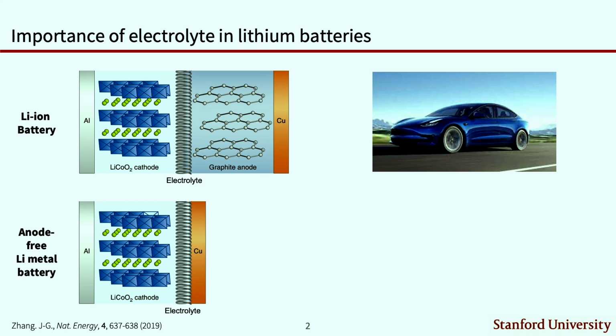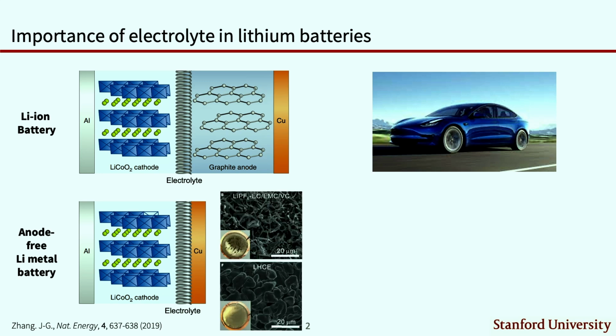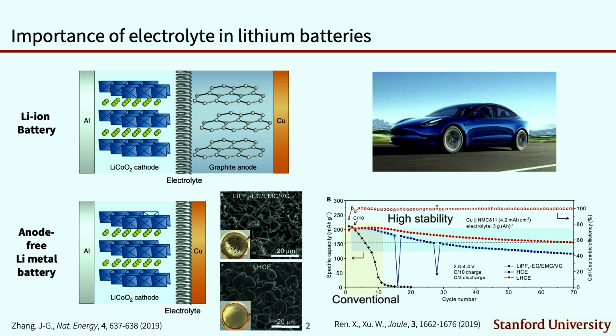In this configuration, you can see the lithium ions, the yellow dots, initially stored in the cathode materials. Upon charging, they will be transported to the anode side and get deposited as metallic lithium. And it turns out that the electrolyte really dictates the properties of this lithium. For example, using two different electrolytes, the deposited lithium's morphology is completely different. And with that, the performance of these lithium metal batteries will be very different.